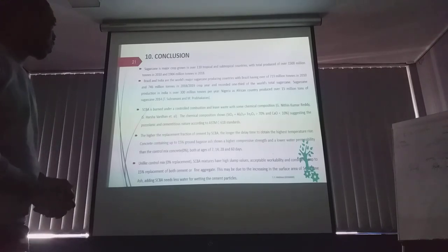Finally, unlike the control mix at 0% replacement, SCBA produces higher slump values and acceptable workability and consistency up to 15%, which is the optimum partial replacement of both cement and fine aggregates. This may be due to the increase in surface area of the sugarcane bagasse ash, meaning that adding SCBA requires less water for wetting than cement particles. This was the end of the presentation.